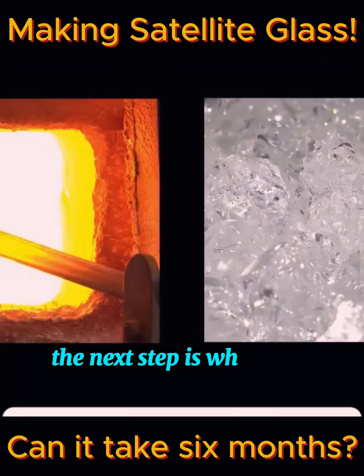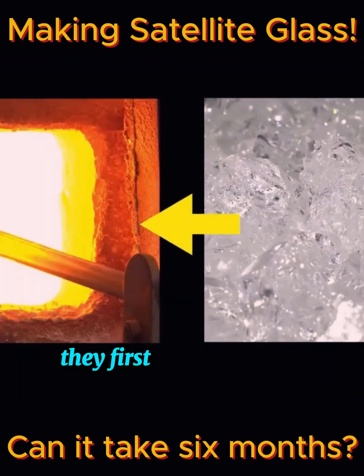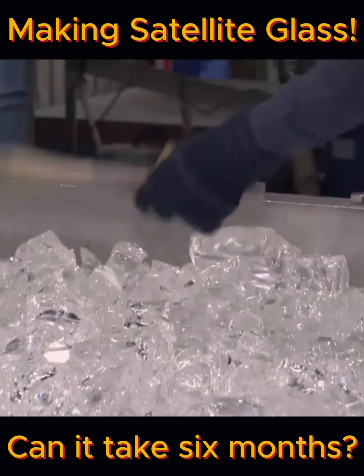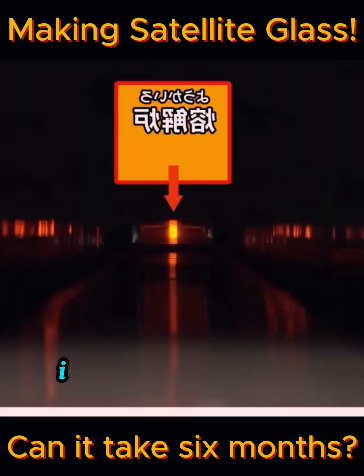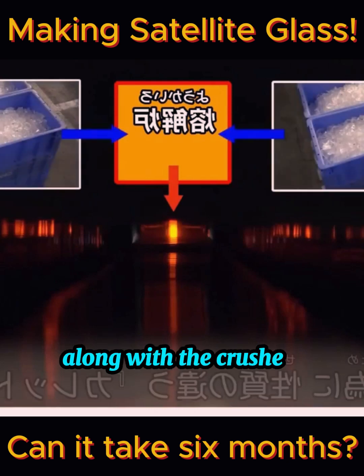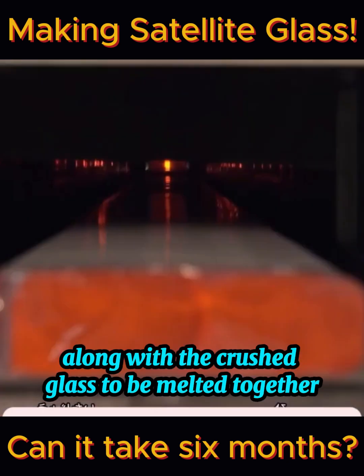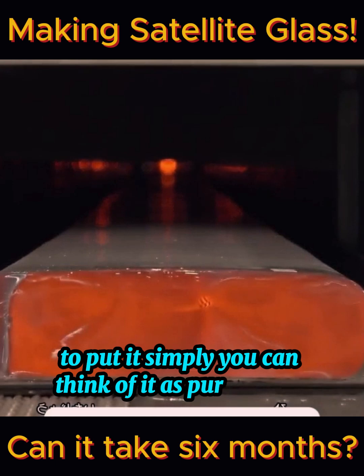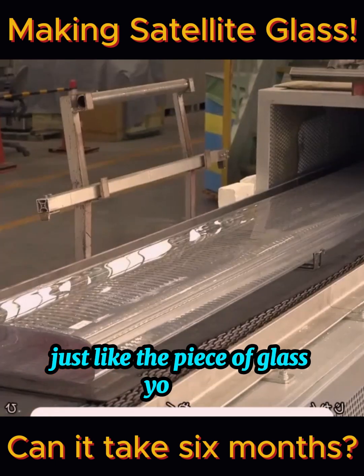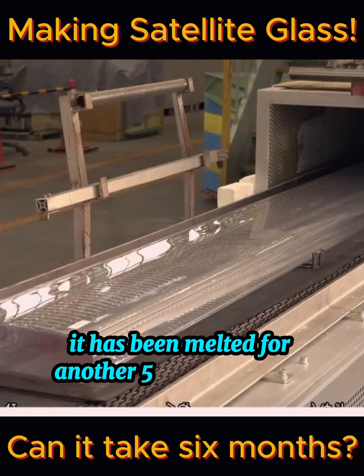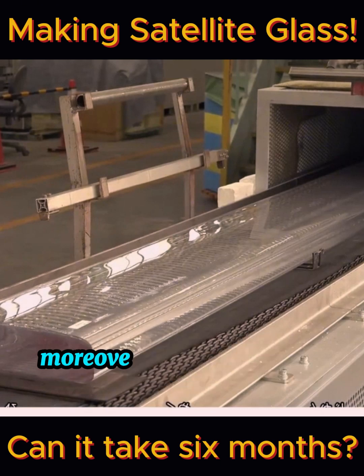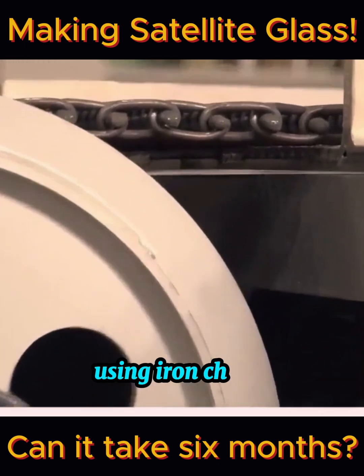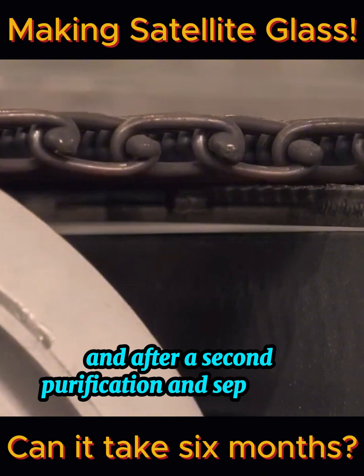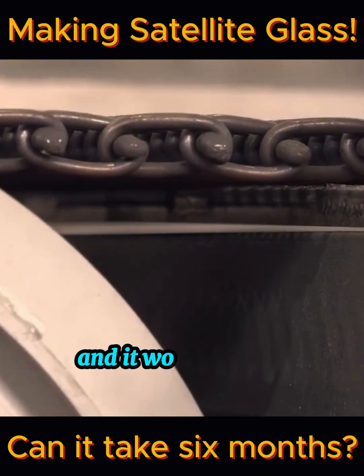The next step is where the most secrets lie. They first categorize the glass by size. Then add 10 different types of finished glass into the melting furnace, along with the crushed glass, to be melted together. To put it simply, you can think of it as purification. Just like the piece of glass you see in the footage, it has been melted for another 50 hours to take shape. Moreover, it has to be pulled out little by little using iron chains, and after a second purification and separation, there are no more bubbles inside, and it won't deform anymore.